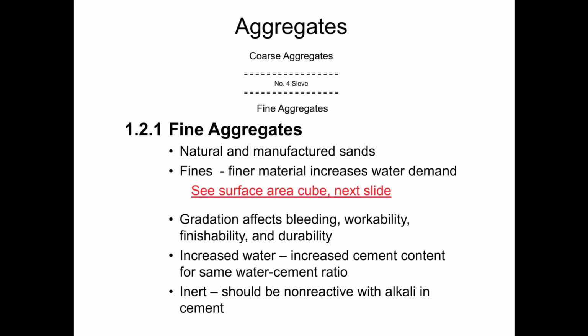All right, so the gradation of our aggregates, because it can have such a significant effect on the workability of the concrete, can also affect the durability. If a mix tightens up, one of the first things that we sometimes do is just add a little bit more water. But when we add a little bit more water, we're increasing our water cement ratio, which is adversely affecting the durability of our concrete. So if we do need to increase the water because the gradation of our sand has gotten finer, then we also need to increase the cement content so that we are maintaining the same water cement ratio.